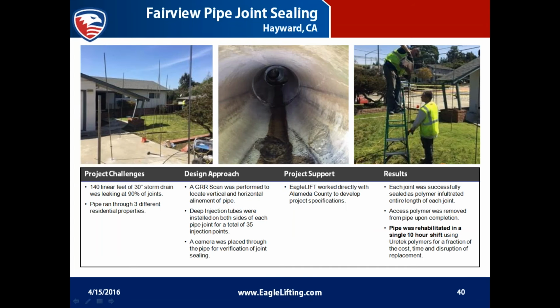In Hayward, California, we did pipe joint sealing, and this is probably a phenomenal example of culvert manhole stabilization without having to trench. You can see in the far left, there was 140 lineal feet of 30-inch storm drains that was leaking at 90% of the joints, which resulted in subsidence of the roadway, sidewalk, and then all the way through the residential district that the storm drain was running underneath. The pipe ran through 3 different residential properties.